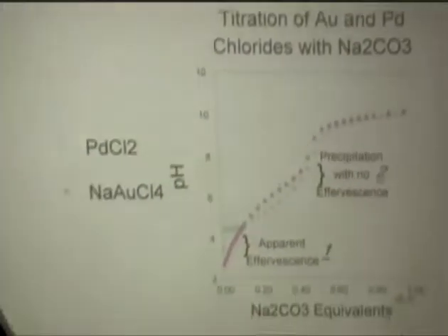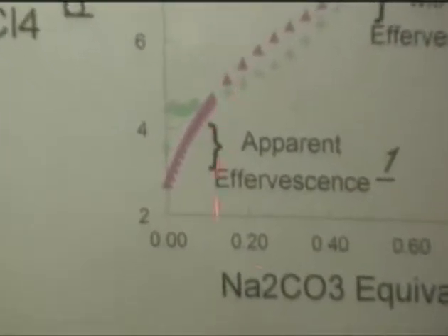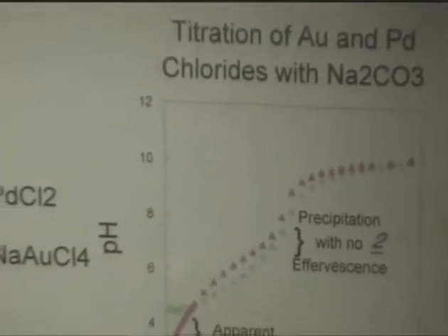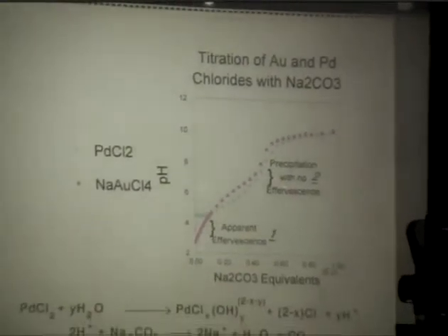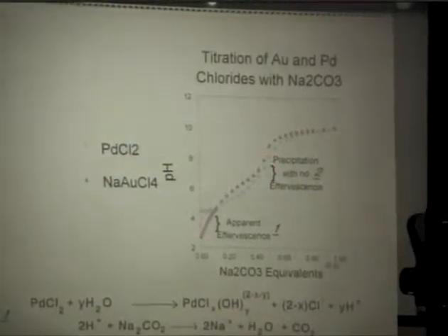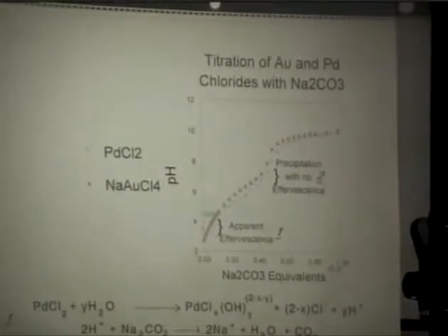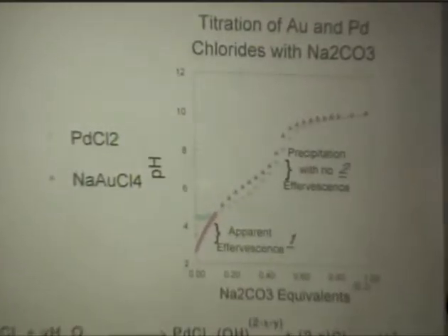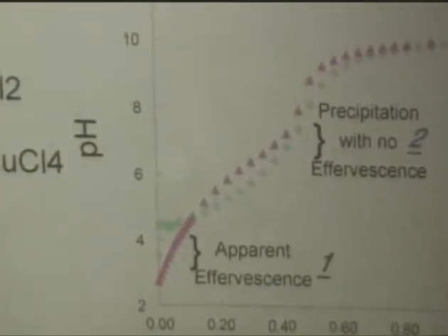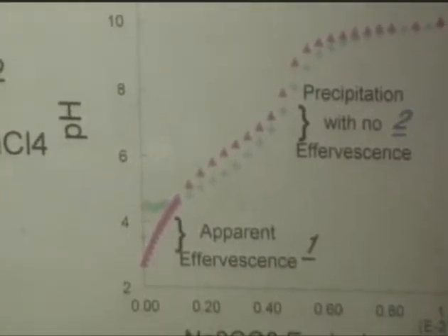Well, what we saw is as we titrated it, when we were at the very acidic point, we did indeed see effervescence. The acid strength of these two metals was so great that the carbonate did break down. But at the point where we saw precipitation of the metal salts, there was no effervescence at all. So we thought, well, that's a preliminary result, and it's kind of encouraging. It looks like we're making the carbonate.